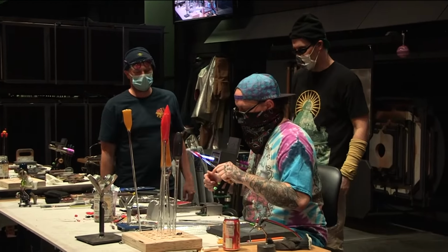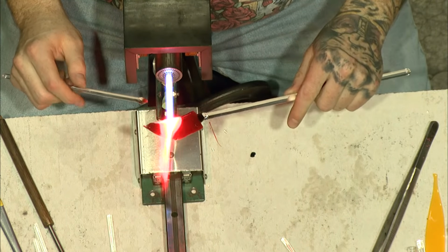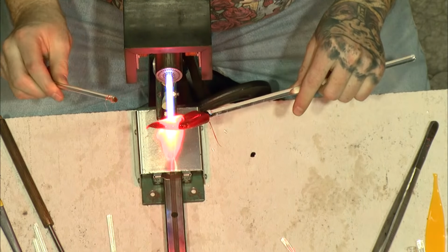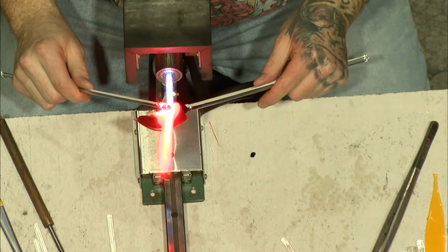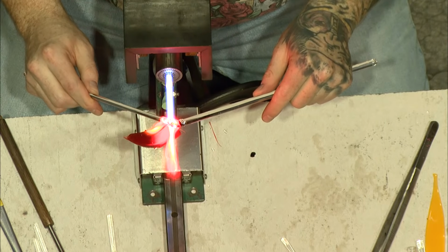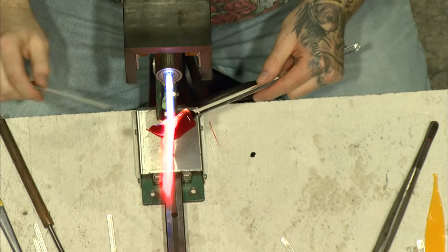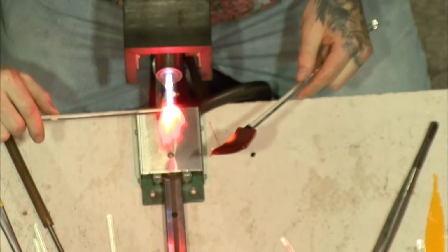I mean, you can use things like metal leaf, silver leaf, gold leaf. Those will fuse and be safe with borosilicate glass. I've seen people get away with attaching copper to some borosilicate glass. I think when the copper is thin enough and if you're cooling it at the right rate, you can get away with that. I don't know that the actual expansion rate is the same, but sometimes you can sort of coax different materials to work together, at least for a while. I can't think of any other metals that I would really feel comfortable trying to attach.